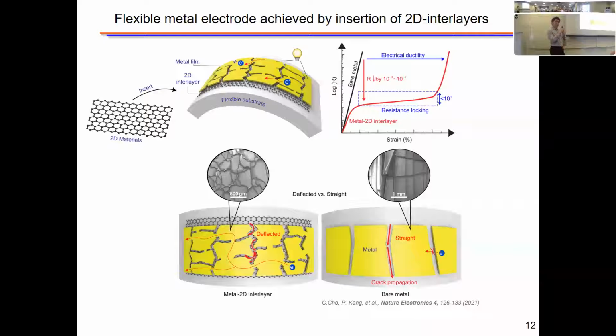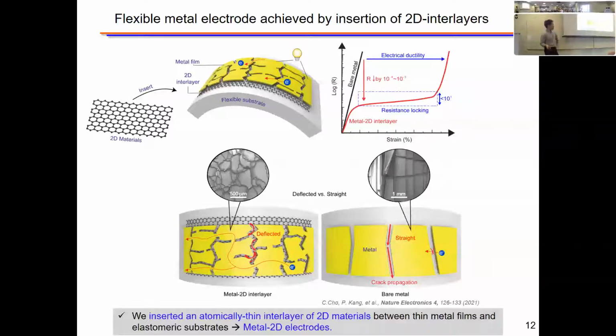We observe an elongation of resistance with strain, which we term electrical ductility. This is analogous to mechanical ductility, which defines the elongation of a material under deformation with strain. Our metal 2D electrode exhibited an extended region of strain with a resistance level reduction of several orders of magnitude compared to the conventional metal electrode.